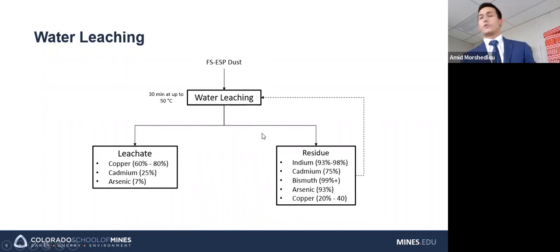And so we get two products from this, a leachate and a residue. The leachate is the aqueous phase, the solution, and the residue is the solid material left behind. These percentages that I'm showing here are recoveries, or the amount of material that reports to each phase. We can see that a good chunk, over half of the copper, goes to the leachate, with about a quarter of the cadmium and not much arsenic. So the leachate is mostly copper.